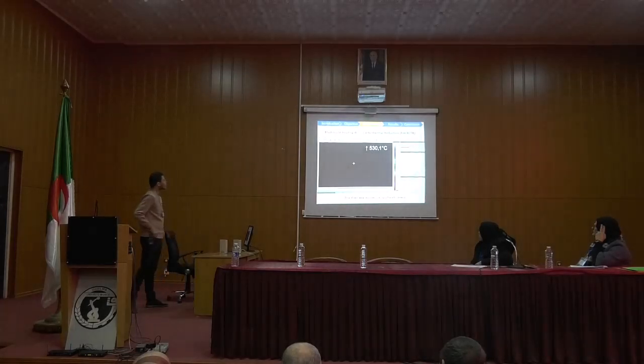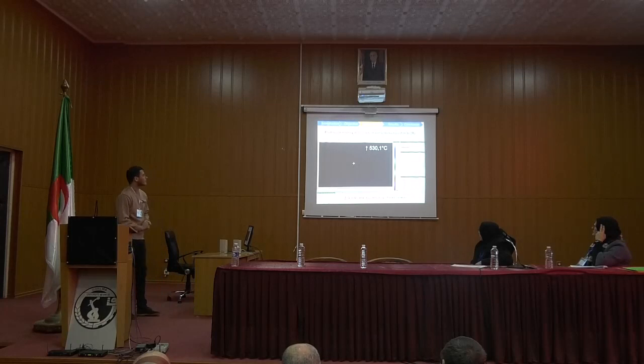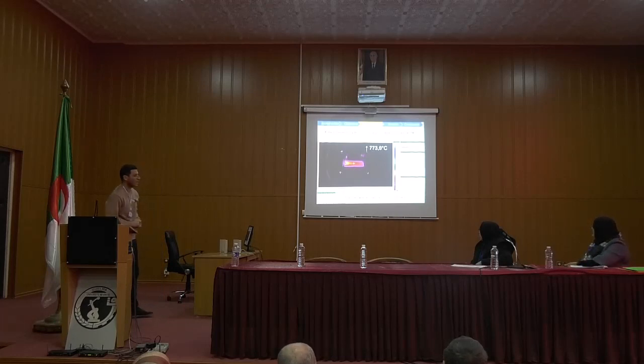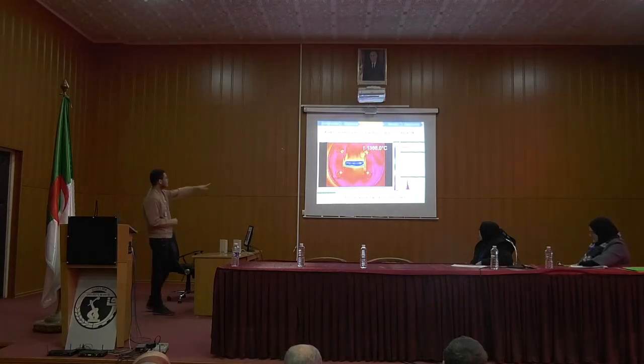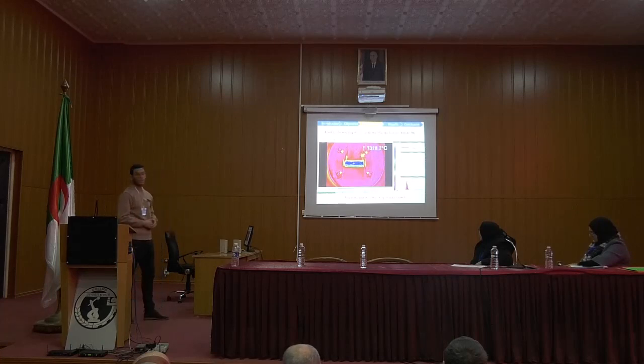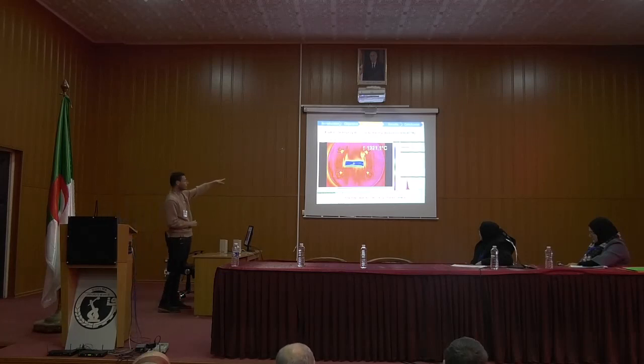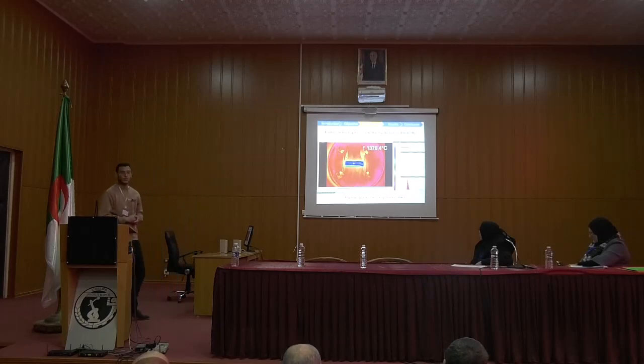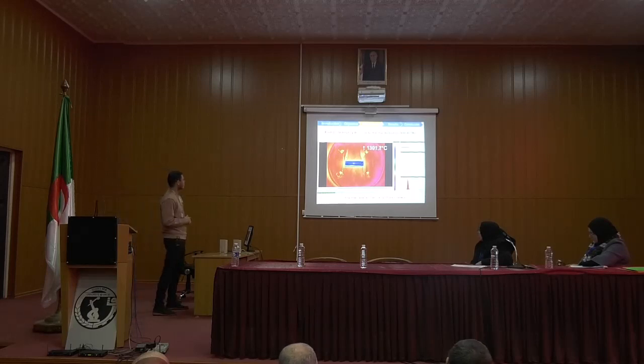So this is a video which shows how this process happened. We use a thermal camera to record how the reaction happened. You can see that the temperature we reach is around 1400 degrees C, which is a very high temperature. This is the sample in the middle, and the temperature reached was very high without the need of a furnace. We just heat it by self-heating. So you can see here the video.